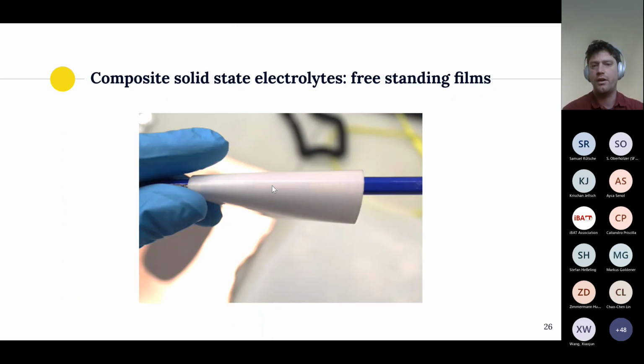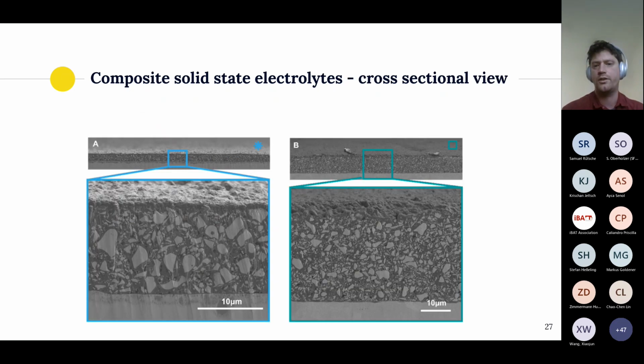Now just a couple of images of the technology itself, of the layers and materials that we produce. This is a freestanding composite electrolyte film that can be shaped and formatted for further battery production, and also a cross-sectional view of a typical composite solid electrolyte layer. The white part at the bottom is a metal current collector as a substrate, dummy substrate, and you can see the composition of these individual films.